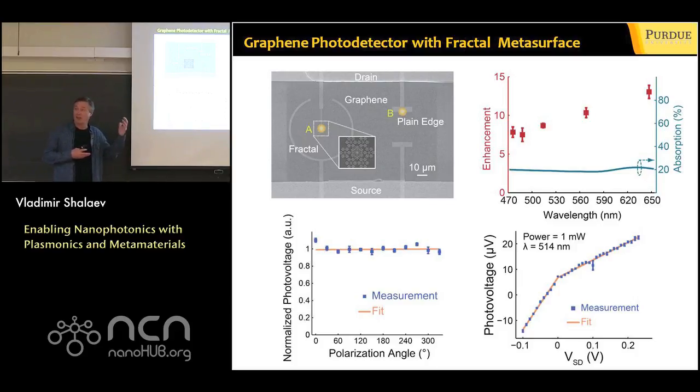We have here Anderson localization for surface plasmons, as we showed quite a while ago with my collaborator, Andrei Sarychev. So it's Anderson localization for surface plasmons, which results in these hotspots providing enhancement in a very broad spectral range. And this idea here is combined with using graphene as a photodetector.